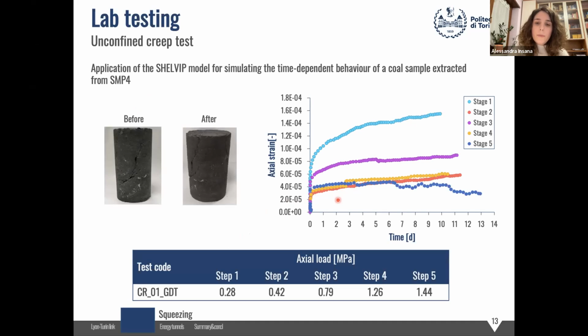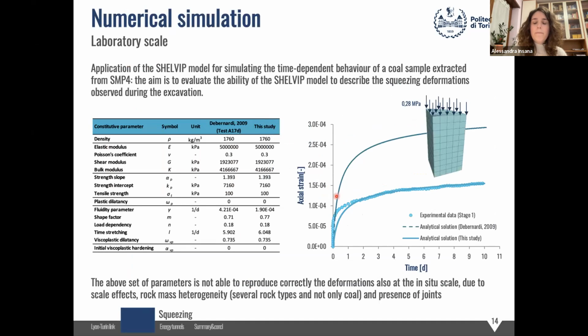So you remember we have talked before about that mechanical laboratory testing, and for example, that mechanical frame. On that mechanical frame, we performed unconfined creep tests with 5 loading stages. And we considered the first stage to illustrate the calibration of the parameters. To calibrate the parameters, we didn't start from nothing, but we had some parameters that had already been calibrated by De Bernardi. So at the beginning we considered exactly the same parameters, but we obtained the uppermost curve, so this one. So we had to change slightly the parameters to better fit the creep curve obtained from the laboratory test. In particular, what we changed was gamma, m, and L, but as you see, we didn't change them much.